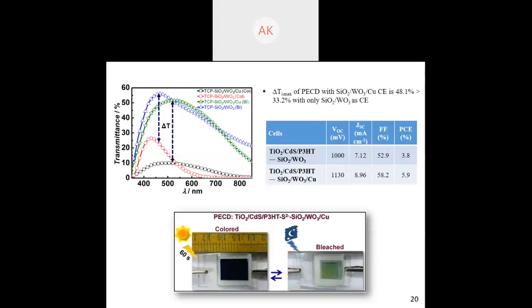Now, why has the lambda max shifted slightly? When we have only WO3, it was in the range of 465 nanometer, the lambda max. But copper nanoparticles have an absorption peak in the range of 500 to 600 nanometer. So the WO3 and copper has the peak max at around 520 nanometer. So you have a power conversion efficiency of 3.8 and 5.9. 5.9 for these kind of cells is pretty impressive, I feel.